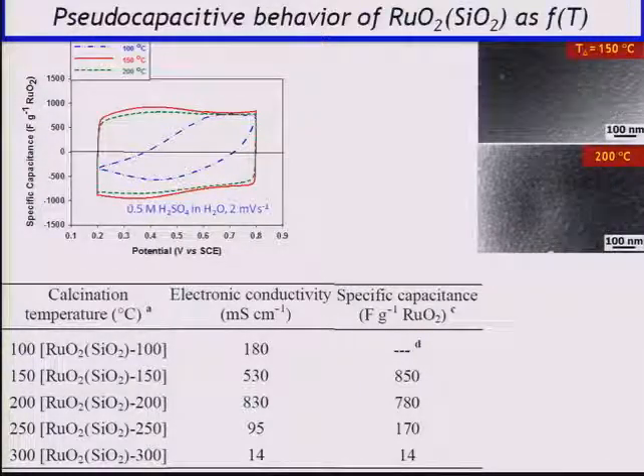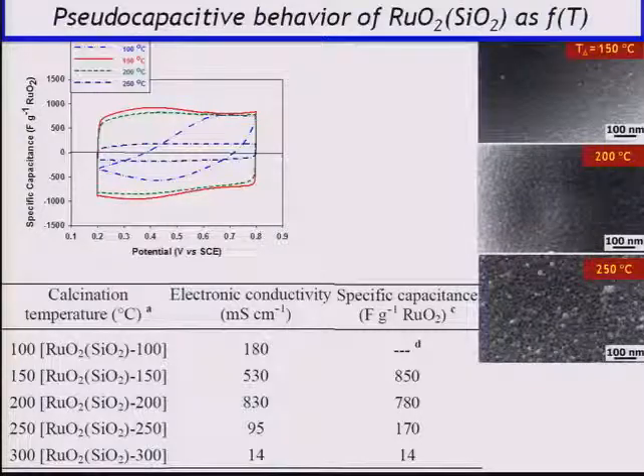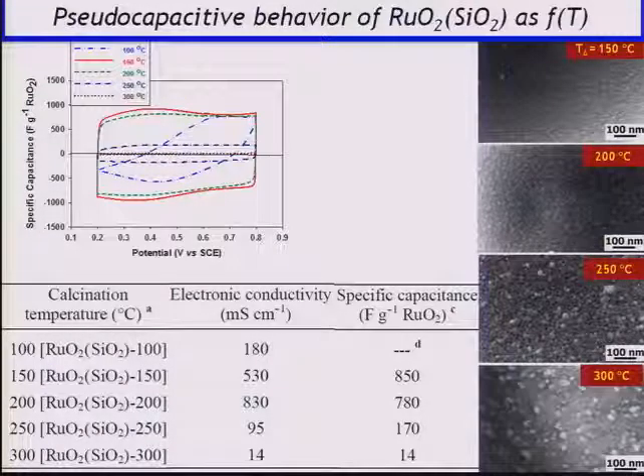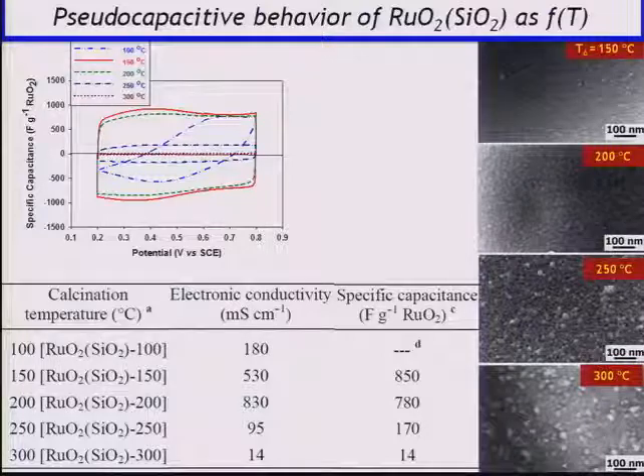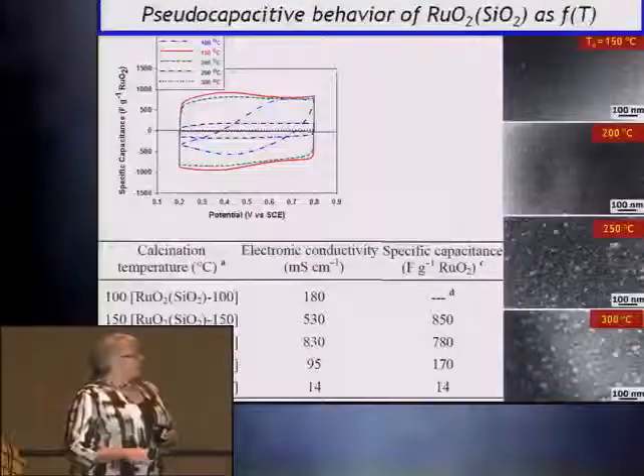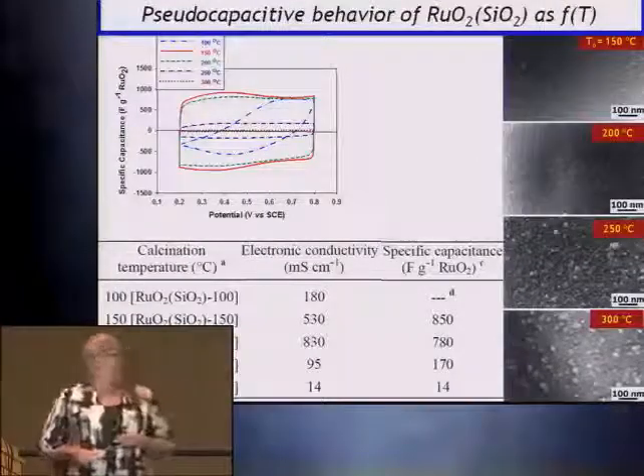centimeter. But once we go to 250, you can see we're ripening the particles, we're changing the morphology, and we've lost a lot of the charge stored. And at 300, we actually have so little ruthenia there, the particles ripen to the point where we can actually see bare silica in the microscopy, lose the conductivity, lose the charge storage.